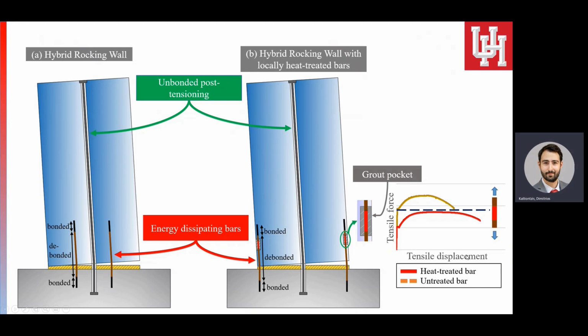As you see from the force versus displacement curve of this bar, the local heat treatment reduces the strength of the bar below the original yield strength, and also increases its elongation. By doing so, we ensure by equilibrium of axial force along the bar axis that the energy dissipation and damage will be concentrated within a specific region located in a grout pocket. We know beforehand where the energy dissipation is going to be concentrated, and therefore we have a replaceable bar section that is more easily accessible, as the bar will be near the end of the wall where we have better access, and we don't have to intervene within a region that is close to the unbonded post-tensioning and will probably require significant cutting of the transverse reinforcement as well.